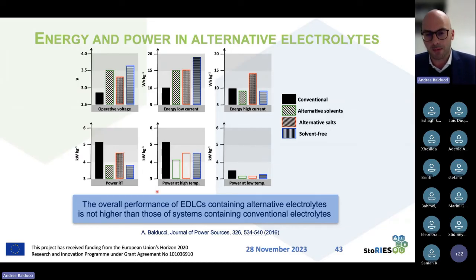When we are going to high temperature, it is a bit less, because normally high temperature promotes ion mobility, and so buffers the system. But in general, at low temperature, the difference can be dramatic. So what I wanted to say with this is that the overall performance of a supercapacitor containing alternative electrolyte is actually not higher than that of the state of the art.